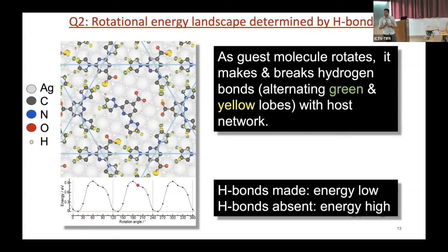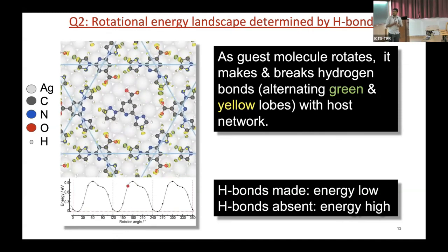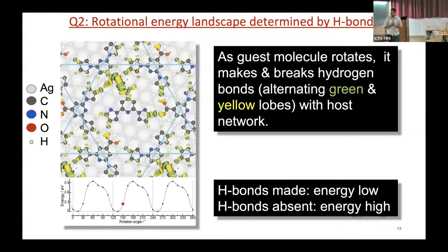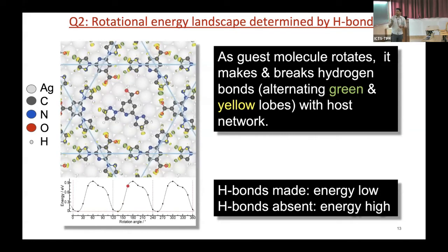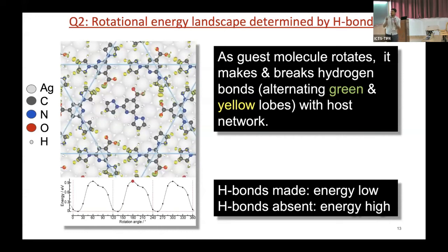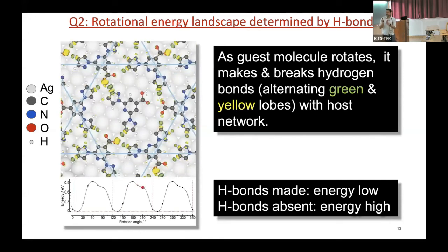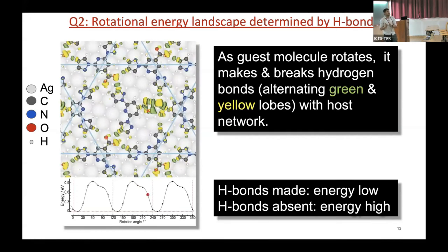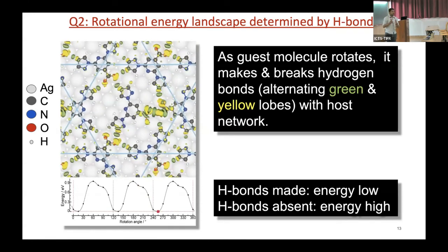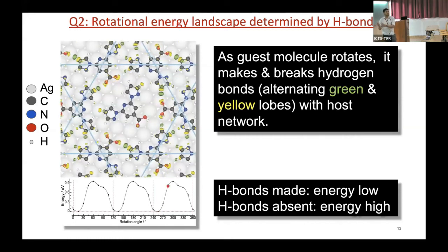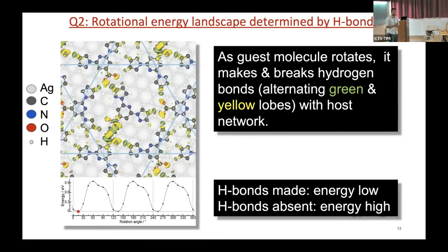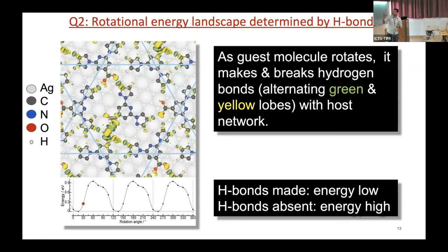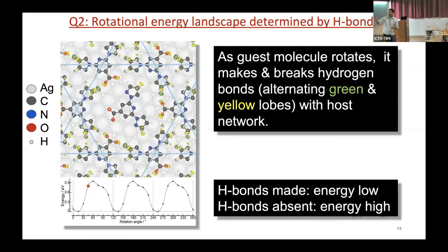No. So basically, there was an option to do NEB calculations, but we haven't done that because we thought it was computationally expensive. What we have done is, at 15-degree intervals, we have relaxed the geometry by fixing the angle. So the angle between host and guest will be some theta. Theta will vary from 0, 15, 30, 45, 60. And there we have relaxed the system. We have calculated the charge transfer plots. And if you see, these rotations are 15-degree interval rotations.